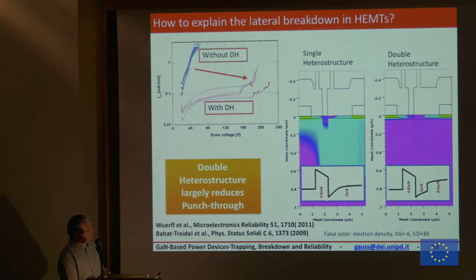So this is the heterojunction that I showed you yesterday and on Monday by Peter. You see the AlGaN barrier, this is the GaN layer, electrons spill over from here. But if I make another layer of AlGaN, so I do a double heterostructure, AlGaN, GaN, and GaN, AlGaN, so I put here again a wide bandgap material, then I try to avoid electrons escaping. And this is a simulation, you see single heterostructure or a double heterostructure. Here the electrons at high voltage are going well down to the substrate, with the double heterostructure, no electrons in the buffer, so everything is confined in the channel. Again, this, by the way, is true for relatively low voltages, less than 100 volts. If I go to 200, 300, 600 volts, even the double heterostructure does not work properly, and the electrons will go there again. So even in the double heterostructure, I need to compensate this layer with carbon or iron.